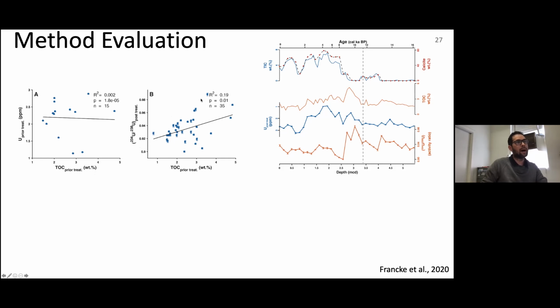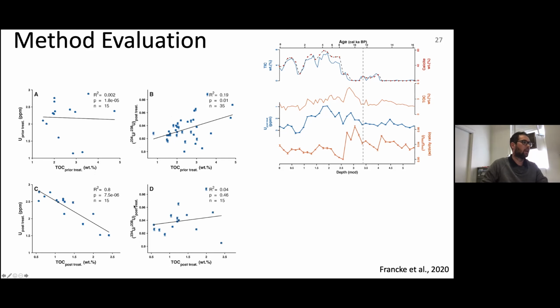It kind of implies there might be a correspondence, maybe because of this early Holocene record there. But if we look at the treated material, we actually find a strong negative correlation suddenly between our uranium concentration after treatment and TOC content. So both after treatment, which is something that just doesn't occur in nature in that sense. So that must be related to our chemical treatment.